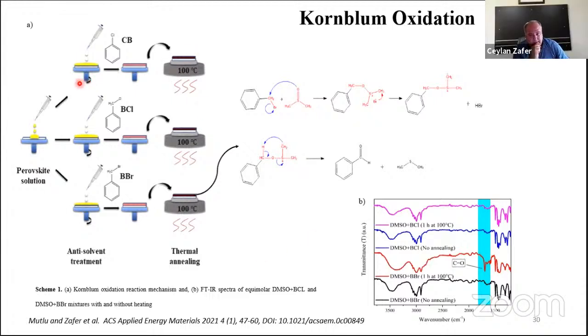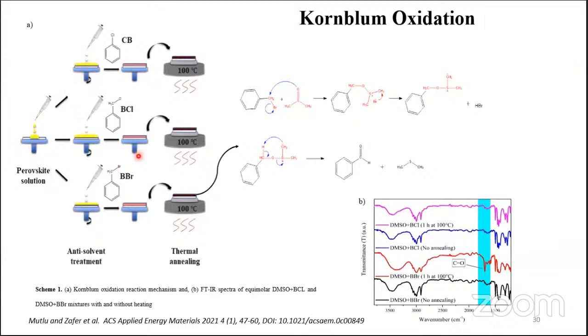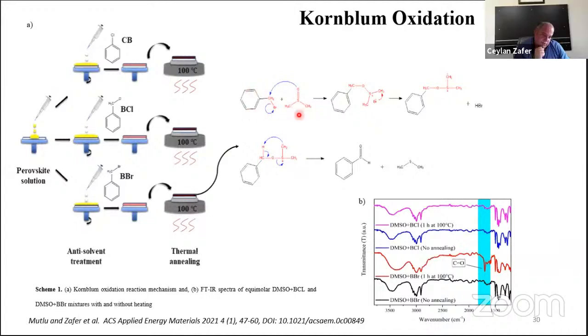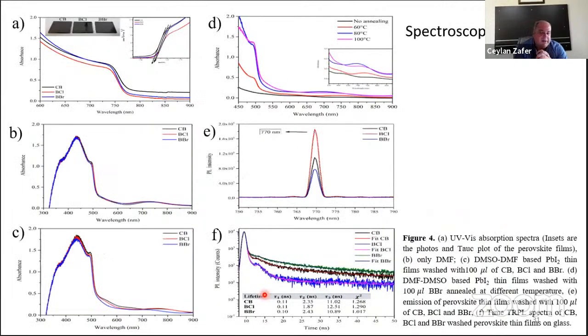And here, within the production process, with this reaction between the benzyl bromide and the DMSO, we get rid of the DMSO by changing it to benzaldehyde and dimethyl sulfide. The benzaldehyde and dimethyl sulfide are easily evaporable at 100 degrees by annealing, and we can get rid of these complexes from the structure. This can be examined with this electronic spectra. Here you see the absorption of the perovskite, and these are the absorptions of the lead iodide washed with chlorobenzene, benzyl chloride and benzyl bromide.